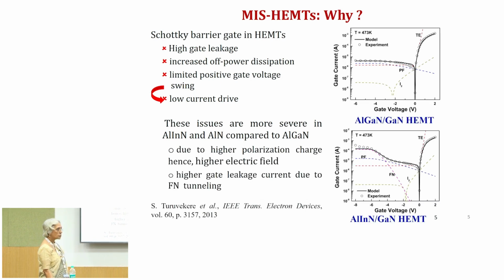So, just to bolster what I said, I have here two sets of experimental data. The top one is for the aluminum gallium nitride HEMT, and the bottom one is from the aluminum indium nitride gallium nitride HEMT. And what is the first thing you notice? You notice that the gate leakage current is more than 1 order of magnitude higher for aluminum indium nitride gallium nitride, and this is because the electric field is so much higher.